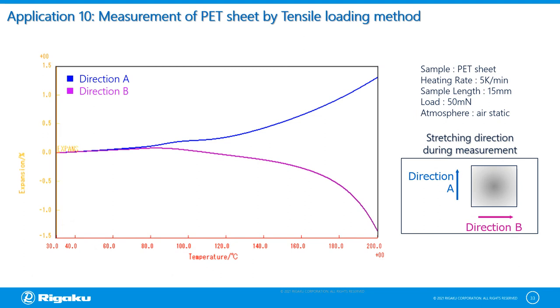This application is a measurement of a PET material stretched in two directions, A and B. Direction A shows an expansion result, while direction B shows a shrinkage result. During processing, the thermally stretched film tends to restore to its former state when heated to its processing temperature. This result indicates that the sheet was stretched in the B direction during processing.